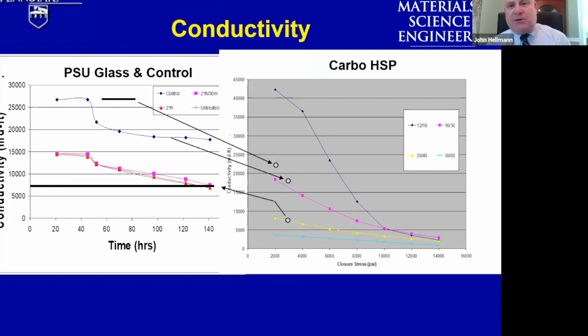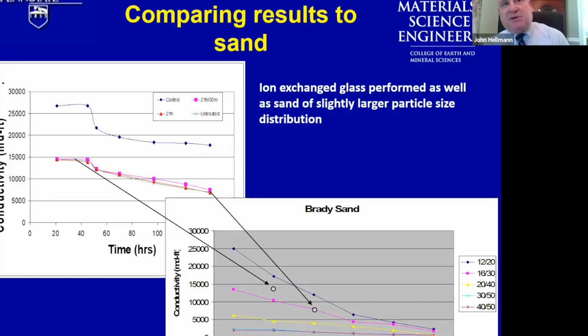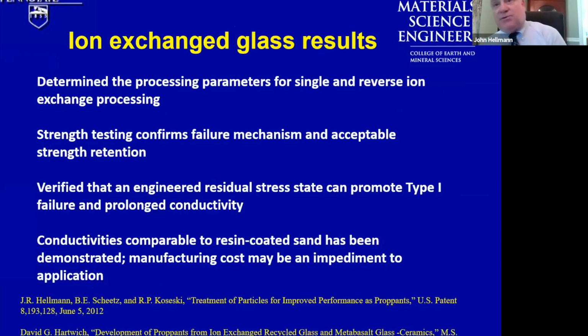So do some of our other materials relative to high strength ceramic proppants manufactured in industry, and they're performing this way without the application of coatings, which is a common practice for high performance proppants in the industry. Coatings are typically phenolic resins, and they're expensive to apply. If you don't need them, don't use them. These materials outperform sands, which is good news. We can use these to prop to deeper depths for longer periods of time. So these were all great results.